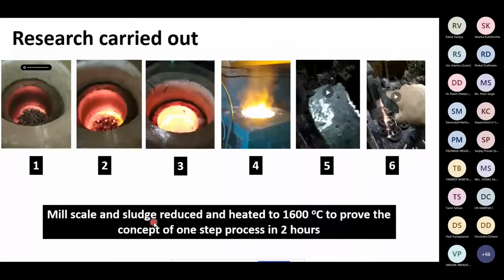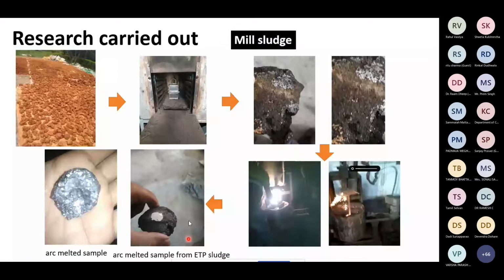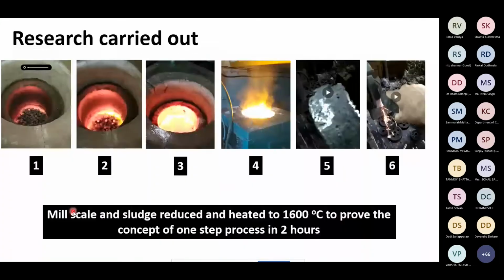Then whatever the 95 to 97% iron sludge, this pig iron is produced from this mill sludge, this sample, and this sample is further melted, further reduced to have this pure iron. So mill scale and mill sludge reduced and heated to 1600 degrees centigrade to prove the concept of the one step process in 2 hours.